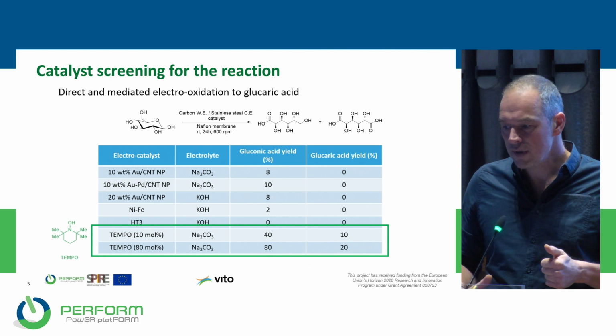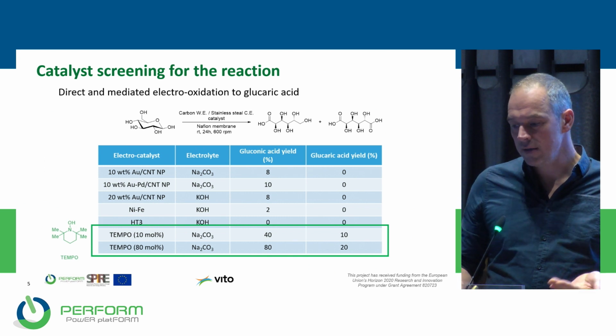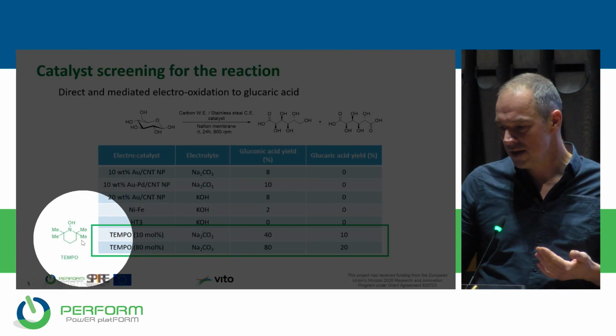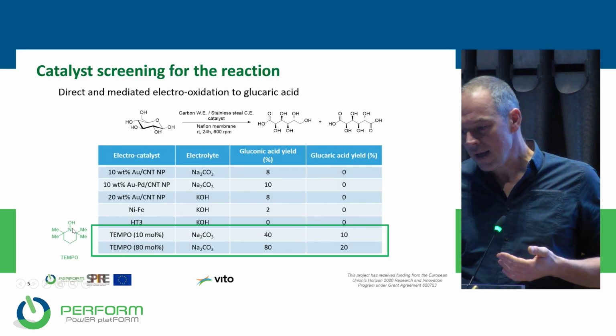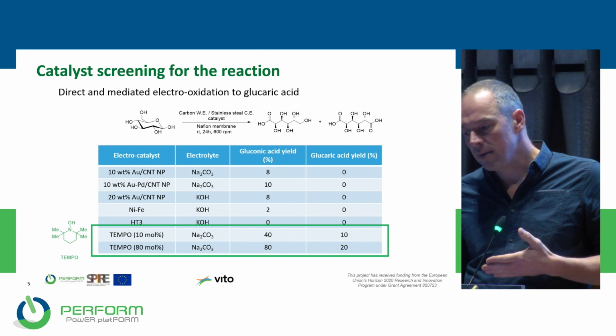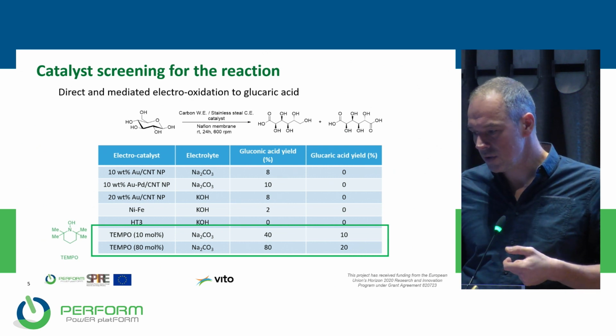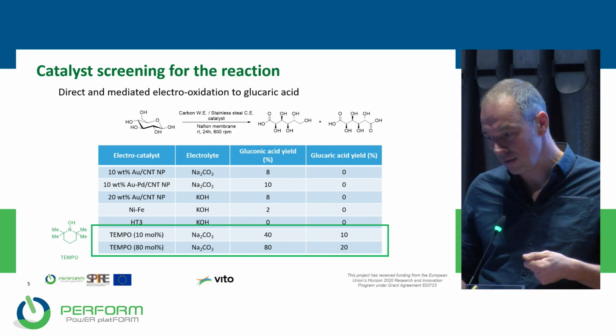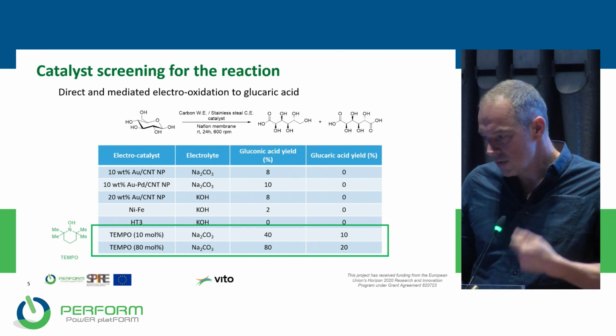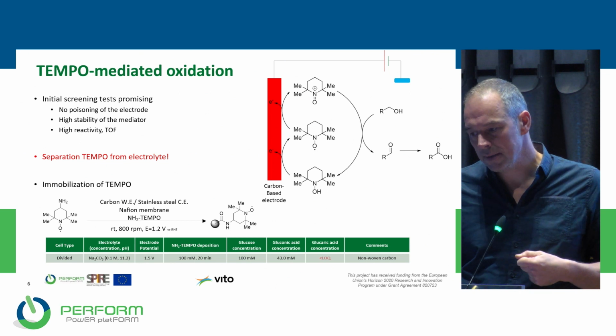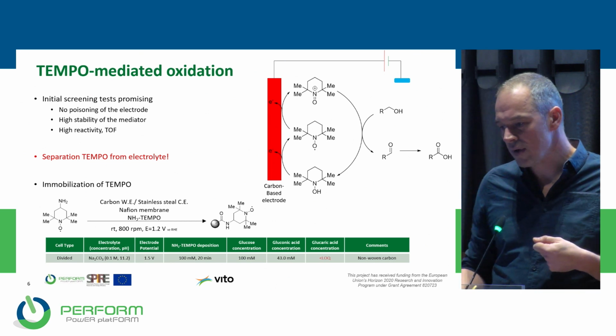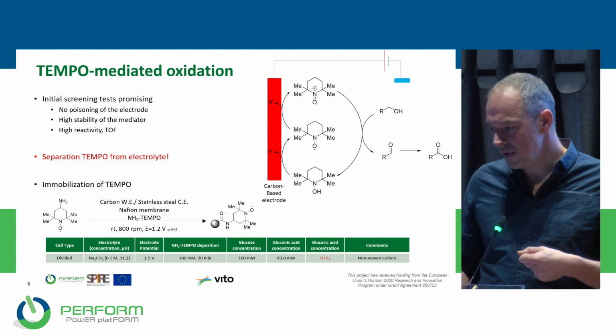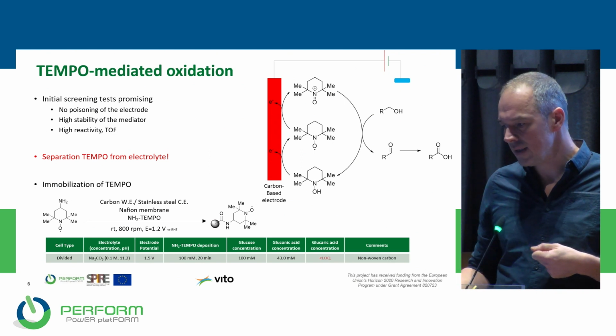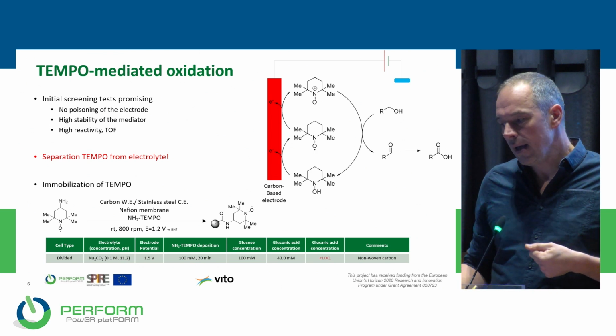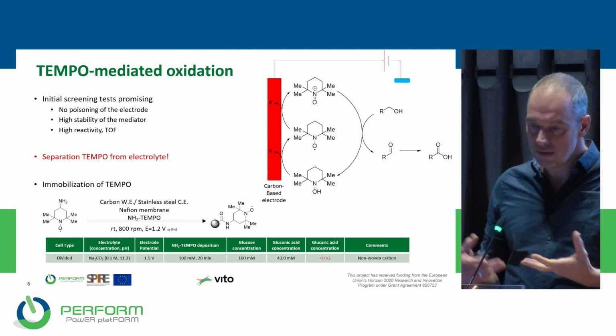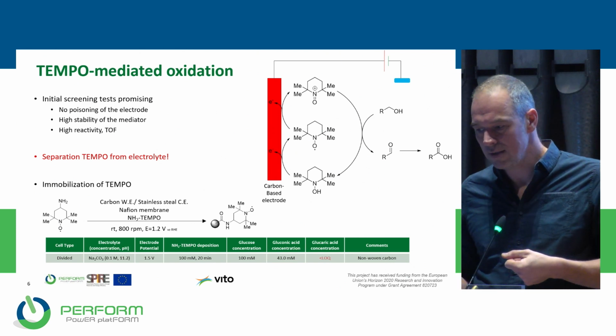So then we shifted towards a mediated electrooxidation, which means that you use a mediator. In this case, TEMPO was used as a mediator. This is the TEMPO molecule, as you can see here. With different mole percentages of TEMPO in a carbonate solution, we found substantial yields of gluconic acid and also glucaric acid. So this encouraged us to move this test further, and we tried to screen it for longer periods of time. So what's actually happening, you can see here on the right. This is the TEMPO molecule being oxidized at the electrode surface, and then oxidizing the glucose in the solution.